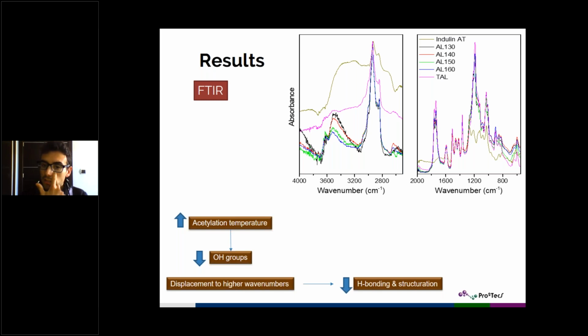On the right, we can see several bands, and we can take a look at the carbonyl groups band that is increasing as a consequence of the acetylation temperature. That was just what we were expecting, as a higher concentration of carbonyl groups is just a consequence of higher degree of substitution. Just again confirming what we saw in the NMR results.